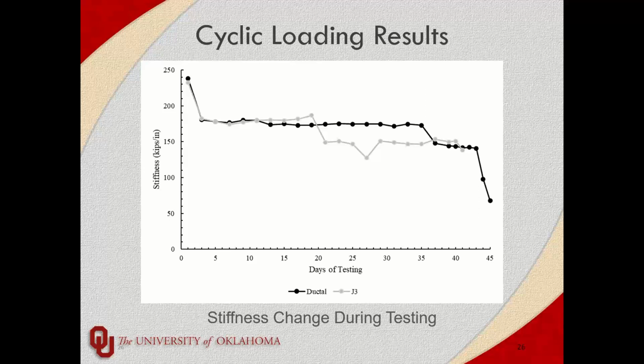But I was very happy with the fact that even though our compressive strength was much lower and therefore the stiffness of the material itself was much lower, in terms of overall behavior, we were able to maintain a very similar behavior to Ductal with J3. So that was a really promising result. Next slide.